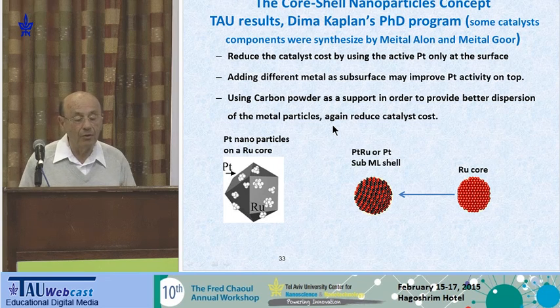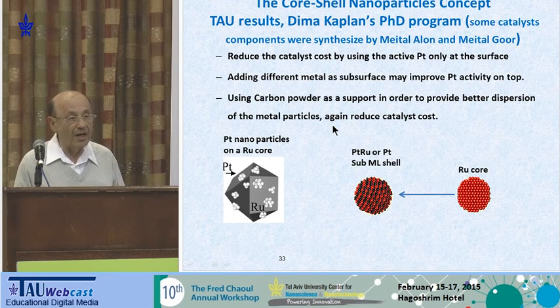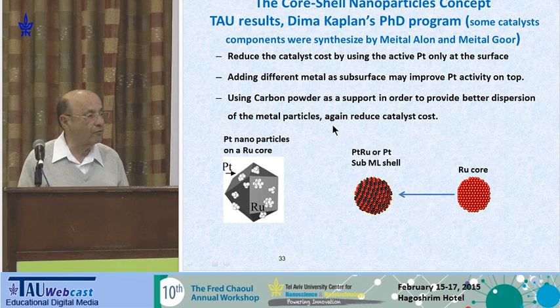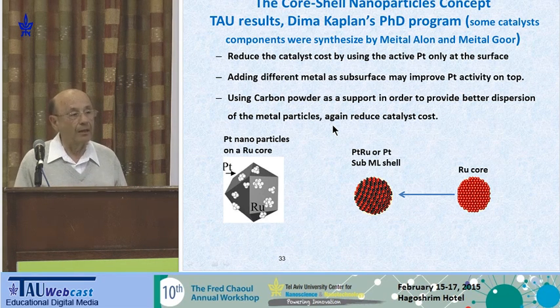Now, the concept is to use a core shell nanoparticle concept. Why is that? Because if you're using nanoparticles, let's say 5 nanometer of platinum, the bulk of the platinum doesn't work. Only the surface serves as a catalyst. So why do we have to use platinum in the core if the outer monolayer just work? So we are picking some less expensive metals like ruthenium, iridium, and other ones, and deposit on them monolayer or submonolayer of platinum or platinum alloy, or build small nanoparticles of platinum or platinum alloy on the surface of this core.